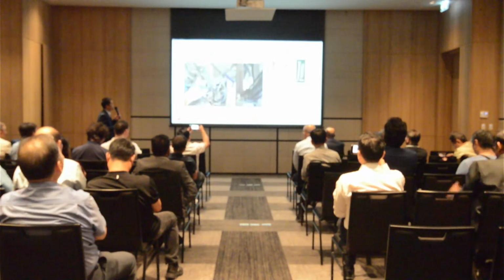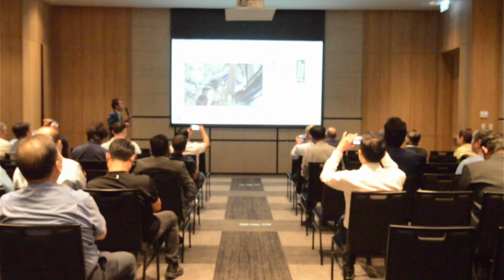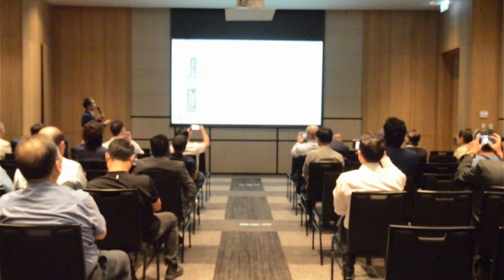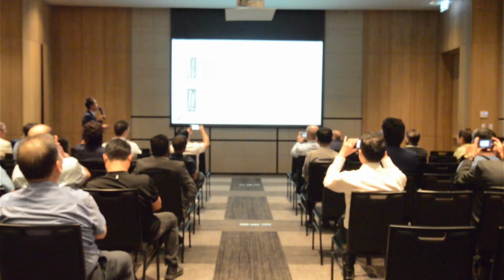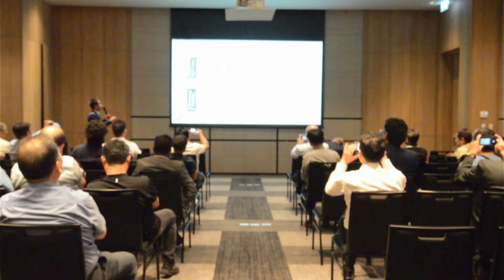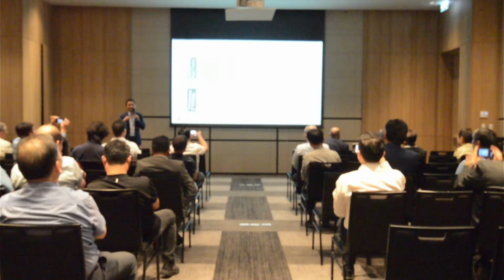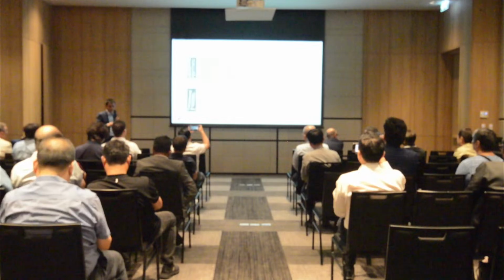And here we also do a comparison. You can see the temperature reduce, the shrinkage and riser reduce, the casting yield increase, and better strength and elongation, fast cycle, and energy saving a lot. And we do this test also to measure the temperature of solidification time, which reduces a lot. Here we don't use a grain refiner, just to compare. No grain refiner and use GISS are similar.